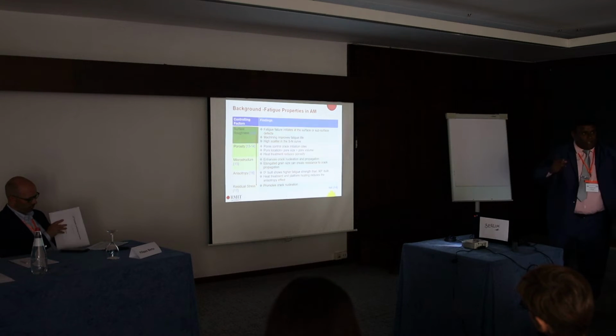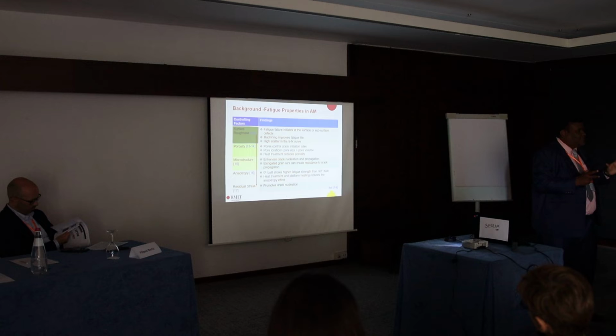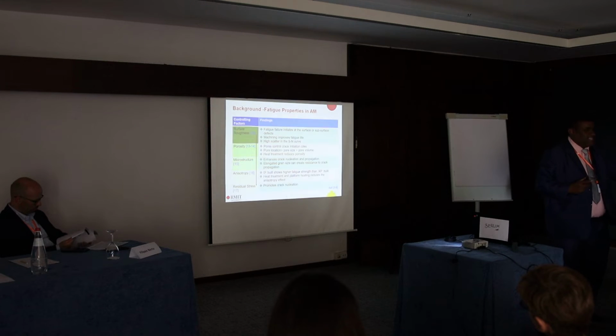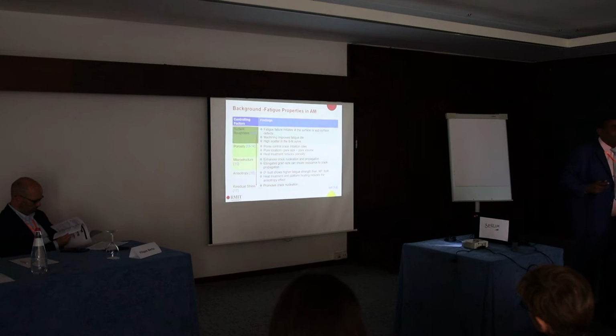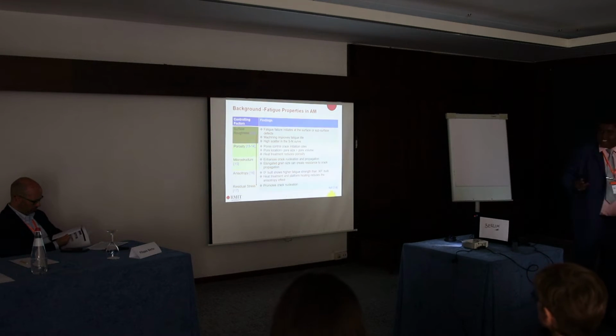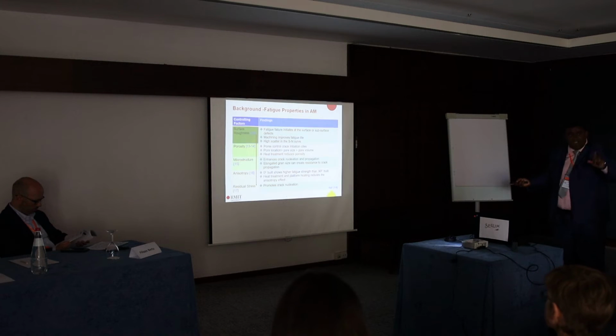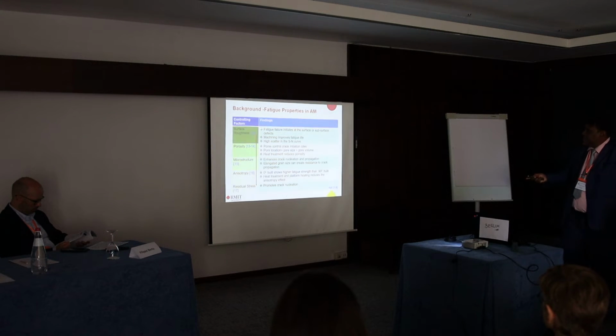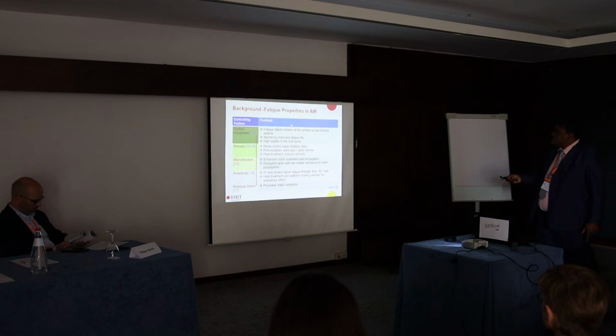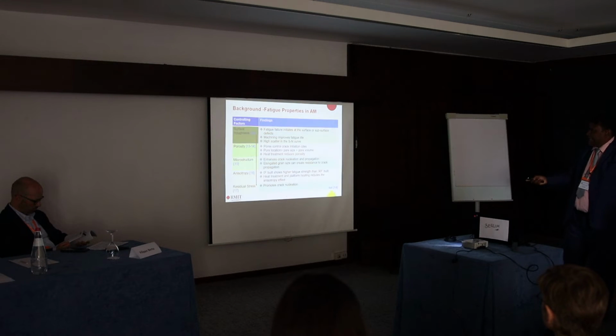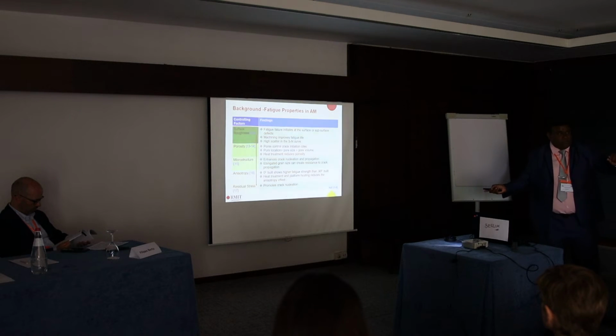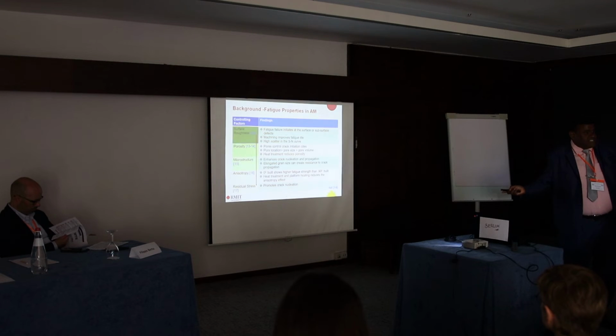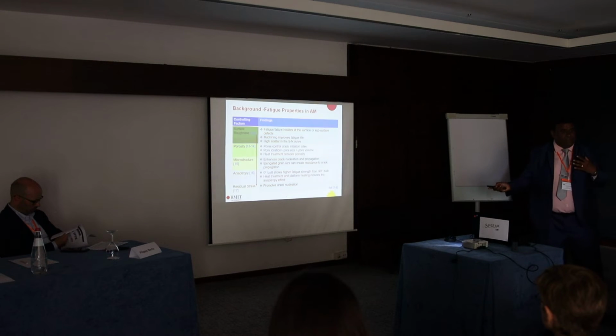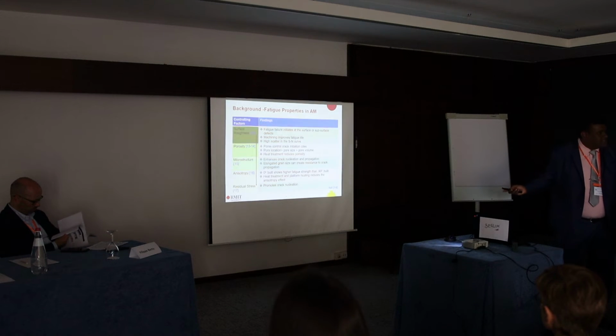Now, because of the complex factors I have shown, we had to first hierarchically identify the most important factor to the least important factor. And that's what we have done in this chart, again based on an extensive literature survey. So what we found is what affects the fatigue properties in AM, and this is based on S-N curves, which is our first goal, but we prefer looking at fracture mechanics.